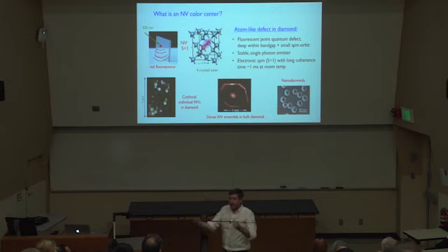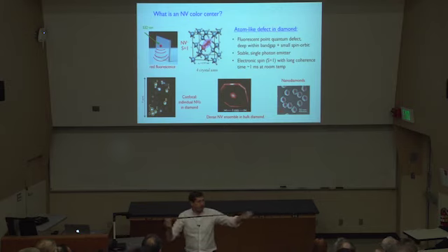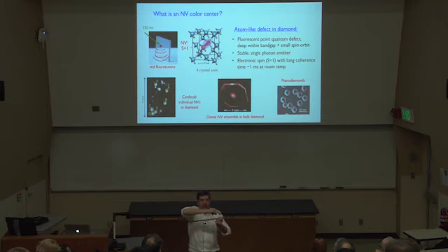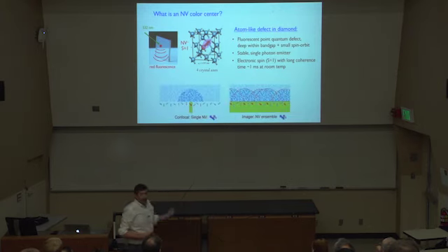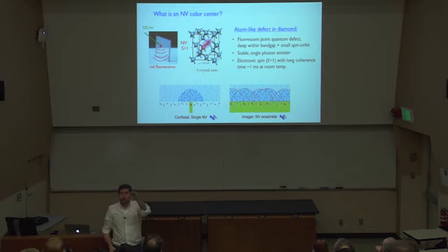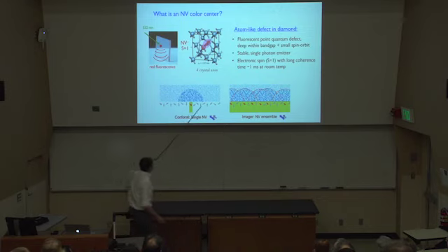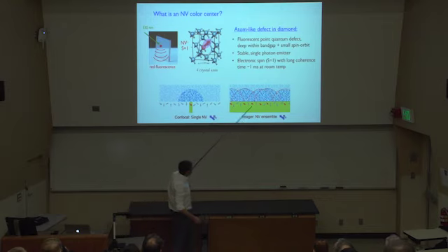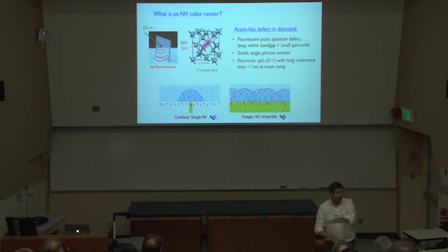Or sometimes you're going to make a kind of nano wedge, like a Toblerone of diamond that might be several microns long and have an NV every once in a while. It sits on the sample of interest, and each NV is an individual sensor, and you can push this thing around and sense. But often you have one of these two modalities, using that bulk microscope slide-like piece of diamond, either with low densities of NVs, and you pick one and you measure it because you want to do nanoscale sensing of some sample of interest right above, where you illuminate with green and take the red light out, or many NVs in a high-density surface layer, thing we call the imager or microscope modality, in which you want to do wide field magnetic imaging with high spatial resolution, now down diffraction limited to, let's say, 0.5 micron or so.